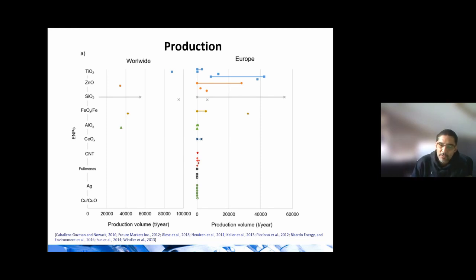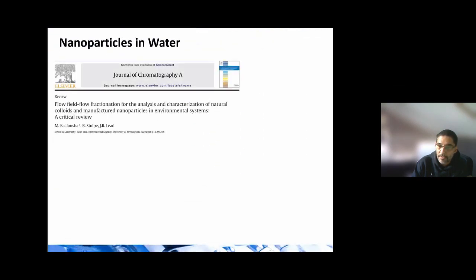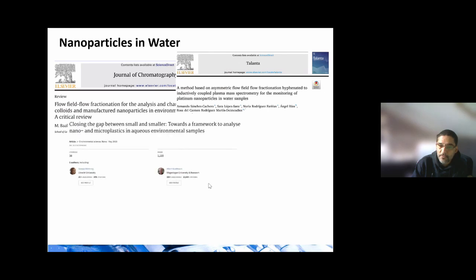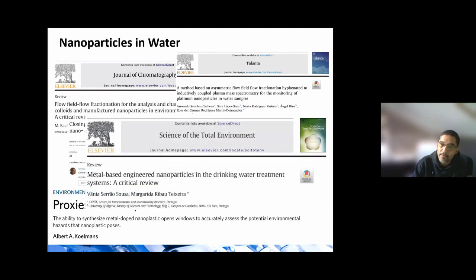To give you an idea, most of these nanoparticles are present in the form of metals, especially coming from the IT industry: titanium oxide, silica oxide. And in terms of production, you can find in many publications that in Europe alone we can produce up to 40,000 tons per year of these particles. If you go to the literature, you find many different papers now about their presence. A lot of them are metal-based particles.